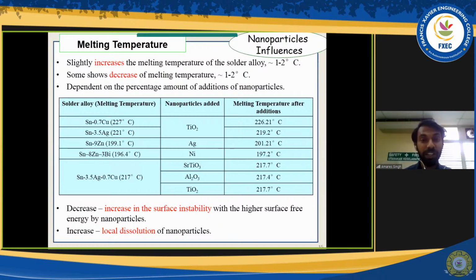People have done these few studies, and we can see certain nanoparticles are added to a certain solder alloy. Let me just give you a highlight that beside the solder alloy, it's the initial melting temperature with the nanoparticles. We can see that some of the nanoparticles have increased the melting temperature, but some of it has reduced the melting temperature. But what is more important here is the increase and the decrease is very minimal. So there's no need for the alteration to the soldering temperature.